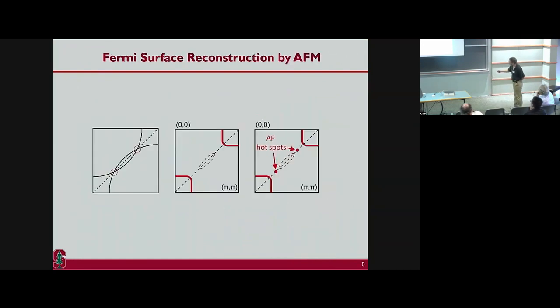Now, here's a cartoon view of this. If you take a Fermi surface and say I have a long-range antiferromagnetic order, then I fold the Fermi surface. Depending on the interaction, you gap this region, and you have a reconstructed Fermi surface. Then, depending on the doping and the details, this part of the pocket could be above or below the Fermi level. What I'm going to talk about for the first part is where this part is below the Fermi level, right at the cusp.